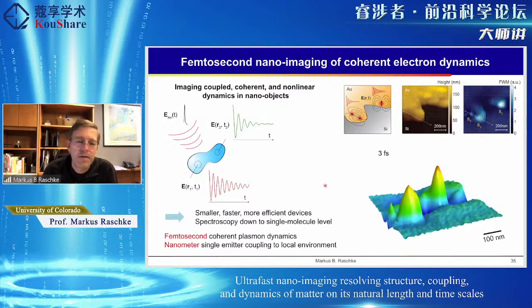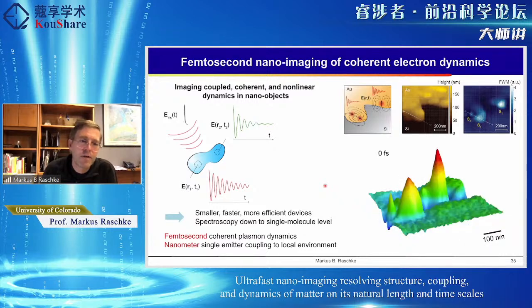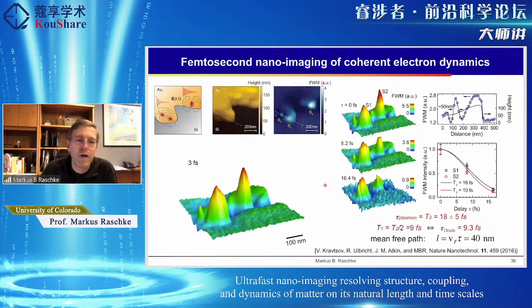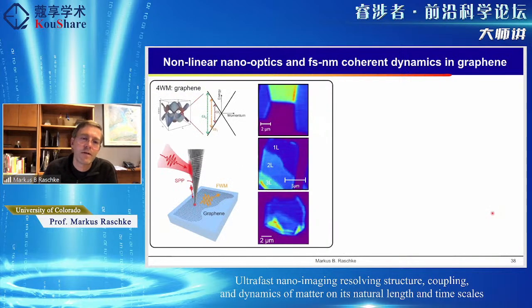And so within a few femtoseconds, really, we are seeing this decay of these plasmonic localized hotspots. And if we evaluate the data and normalize by looking at the signal in this way, normalize to the strong emitter, then you actually see that there are differences in the time evolution of these different plasmonic structures, and then we can determine spatial heterogeneity in this ultrafast Drude carrier response on this few femtosecond timescale. So this is fundamentally informing on a lot of these elementary electronic excitations in the metal, and we want to then apply this, for example, to graphene.